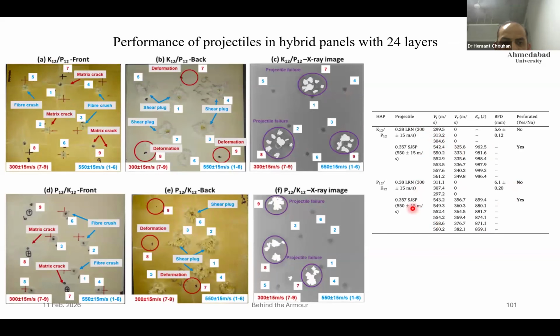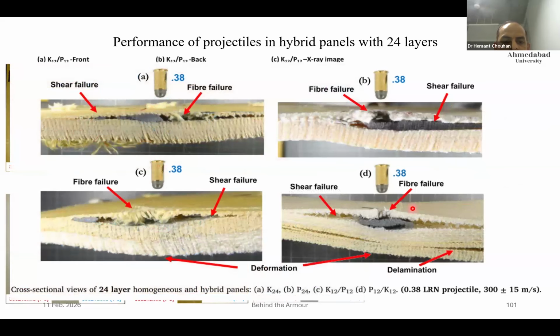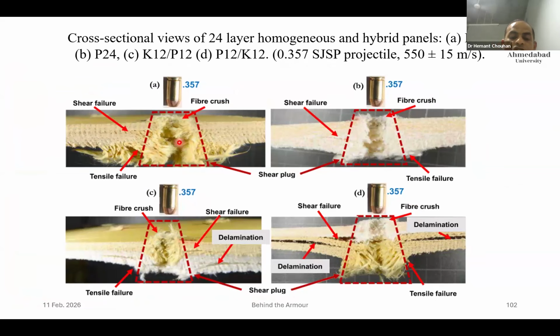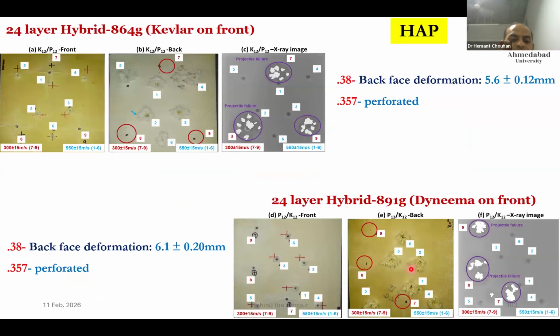So these are quite good studies that can be done for a variety of existing as well as newly designed materials. And this is how the damage propagates. And this shows how the damage happens when there is a residual velocity. In case of Kevlar, it is fiber crush, shear plug, shear failure and fibrillation. Whereas in this case, the fiber crush and the way it is happening and the delamination plane are significantly different. For the hybrid system with the front of UHMWP and with the front of Kevlar, things are slightly different, and that is the reason your residual velocities were slightly varying. But with this kind of hybridization, we can develop better solutions.